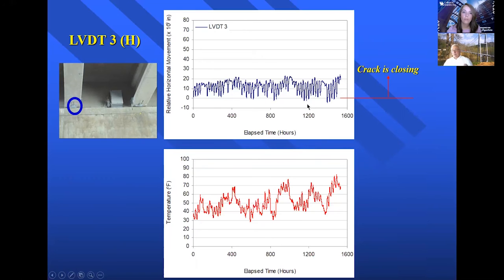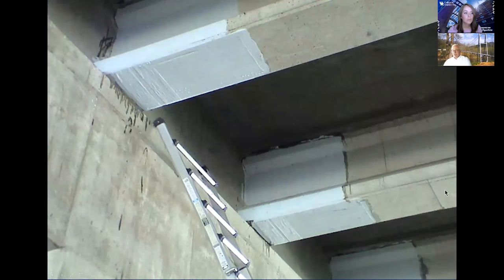But we were able to monitor it for a whole year because we didn't see any danger of any collapse of a beam, and we noticed that the crack really is not growing. So we designed a retrofit such that it will be the least expensive approach to this repair. We decided to close this crack and move any future cracks away from where the fabric ends, somewhere in here. This is a much safer area to repair on the beam as opposed to the one right near the support.